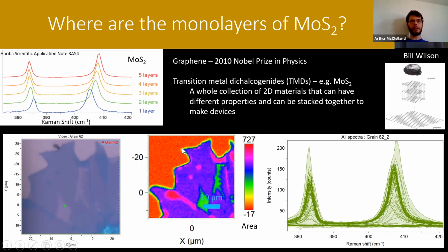Doing the Raman spectroscopy, you take a spectrum from every single point. And if you look closely at all these spectra stacked on top of each other, you can see that there are some, like over here, where the peaks have shifted up. Here, the peaks have shifted down. So you can take the distance between each of these peaks and plot it out, and you can see where the single layers are, where the multilayers are, quite clearly. You can also do the PL map of this and then see where the strain is, because that will change the PL.